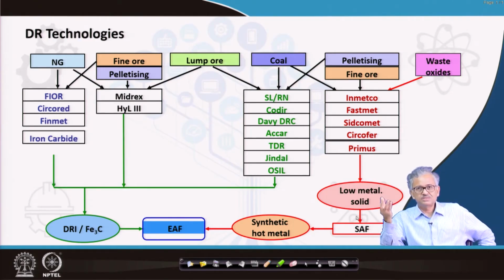When you separate the gangue, during this process you also reduce to some extent, since it is 70 to 80% metallized, a lot of iron will be connected with the oxygen in the form of wustite, FeO. So you also reduce using some coke, some coal, some kind of carbon, you can reduce this FeO back to iron. It will have some reducing atmosphere, and when you do that, some other impurity also will come into the liquid iron, and whatever you produce is called the synthetic hot metal.